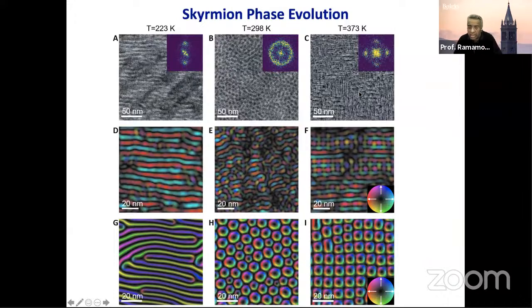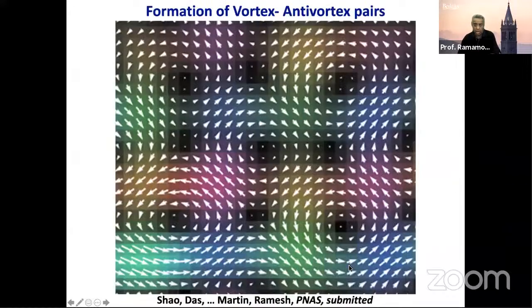The other thing that happened was when they start to go to high temperature, they were starting to stretch these membranes, the samples a little bit. And then it started to order. And you can see that in calculations also, they start to order. I'm going to show you a better image of that. This is the actual TEM vector map, the so-called 4D STEM image. You could see that the vortices are here. These are the rotating patterns. This one is rotating counterclockwise, counterclockwise, counterclockwise. But the guy in the center is actually rotating clockwise. So you now have a vortex lattice. Of course, it's very locally ordered. We still don't know how to make it ordered in long range.